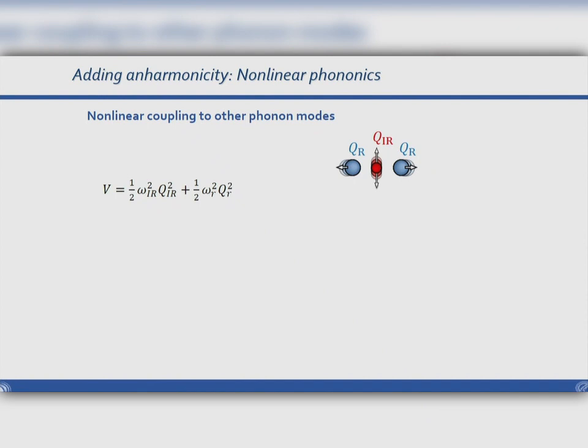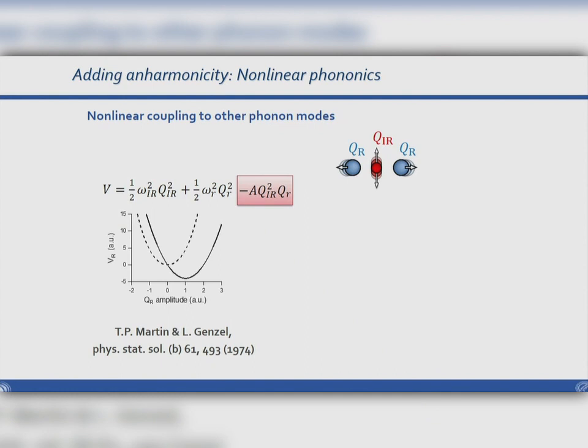But how can we use this to control functionality? So far, I've only shown you that atoms oscillate around equilibrium positions, and this probably will not change anything. So what you now should take into account is a second mode, which has a different symmetry. Now this is a Raman mode, okay? And what you learned at school is that in linear order, they cannot interact with each other. However, decades ago, the following scenario was proposed, called ionic Raman scattering, which tells you that in the lowest order, there can be a coupling between an IR-active mode and a Raman mode in that system, which is proportional to what we call Q_IR squared Q_R, which is quadratic in the amplitude of the driven mode and linear in the amplitude of the coupled mode.